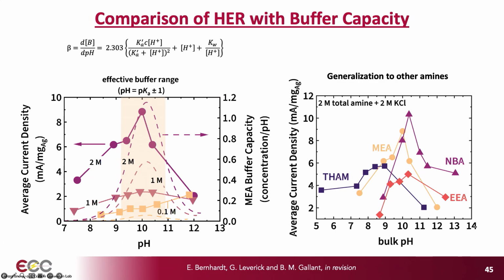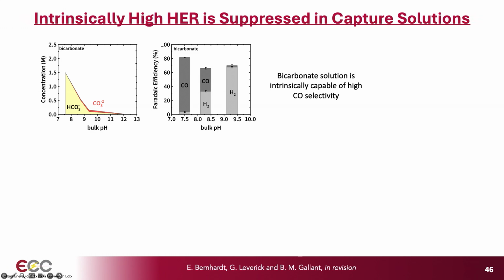But also fortuitously, we see that as we move away from that region, if we operate our reduction reaction somewhere over here, we can actually avoid the high hydrogen evolution activities if we design our systems well enough. And I just want to say that this finding was actually universal across quite a number of different amines.